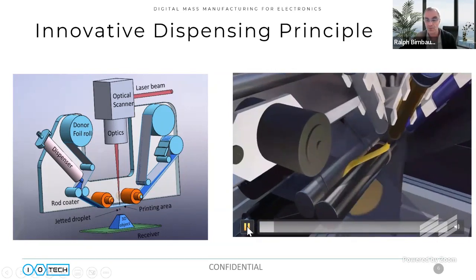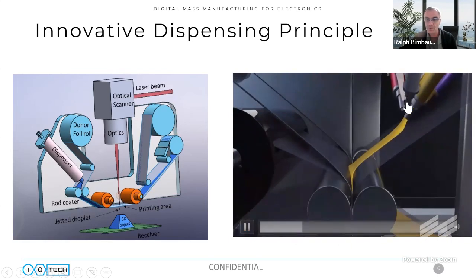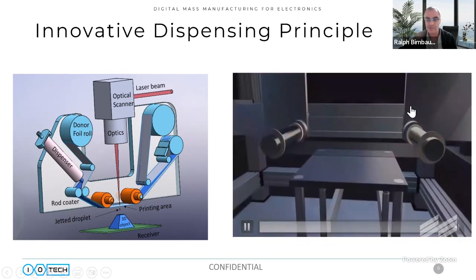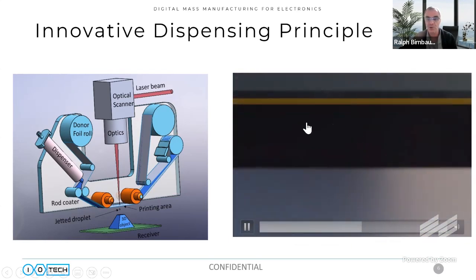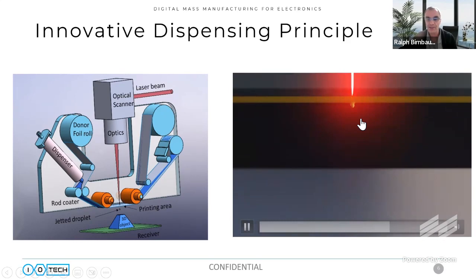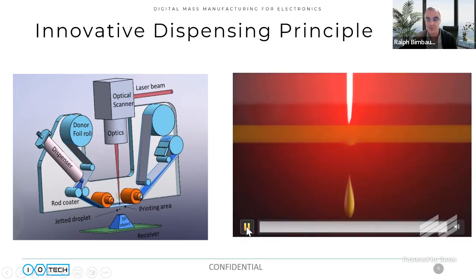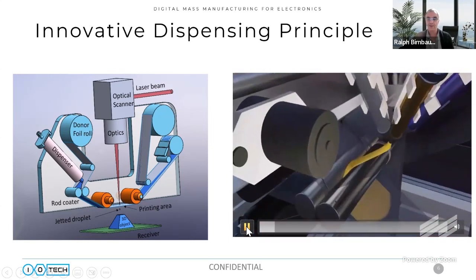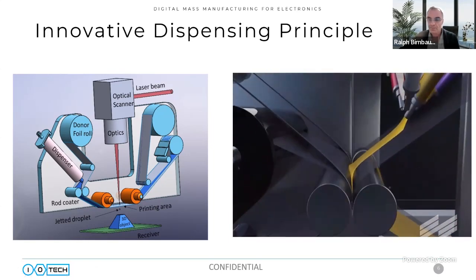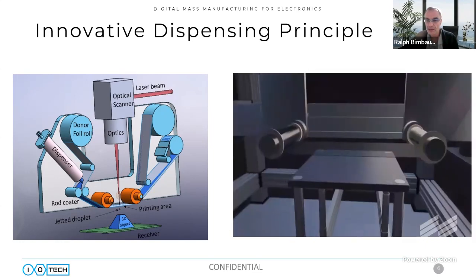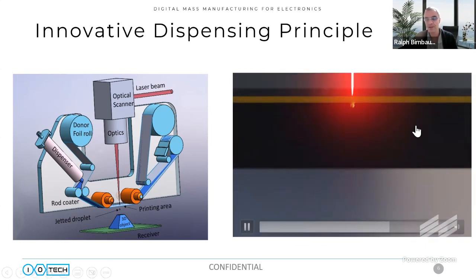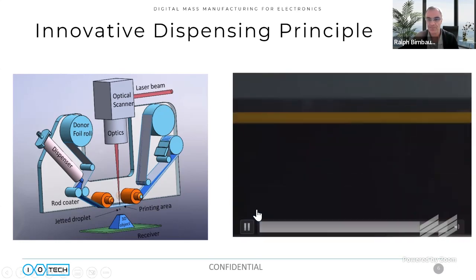In video form on the right, you see the material being deposited onto the carrier, goes through the cylindrical rolls underneath the laser, whereby a drop is released onto the substrate below. I'll re-show that again because it goes quite fast. The carrier carries the material under the laser. There's that brief pulse of energy. And there you go.